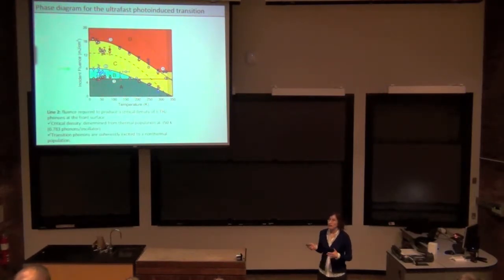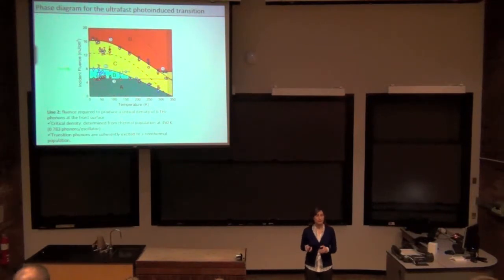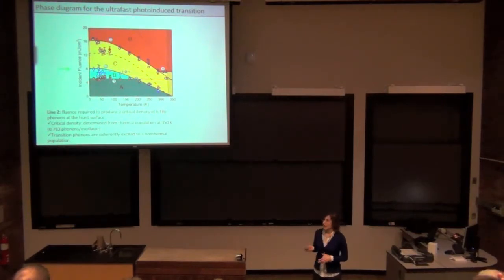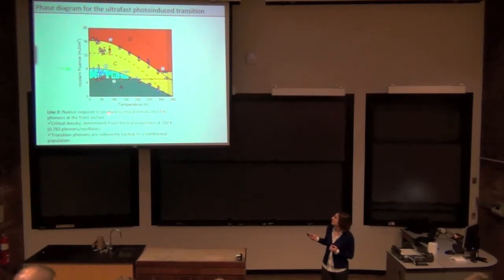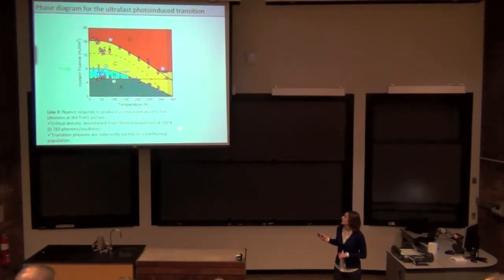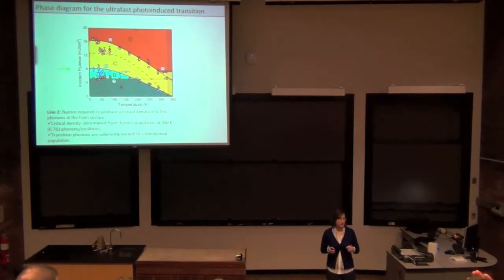Again, we know that at 350 degrees Kelvin, the sample is metallic; the transition is driven by temperature change. We can calculate, just from the thermodynamic distribution, the critical density of 6 terahertz phonons at this transition temperature. We know the critical density that is needed to drive this transition thermally.